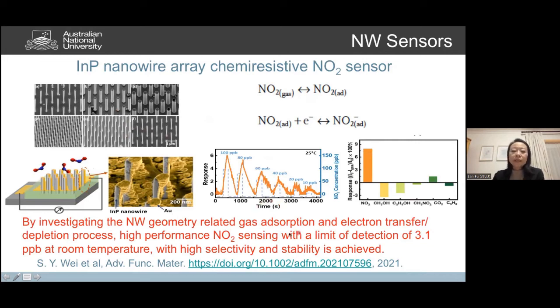We're able to achieve a limit of detection down to the 3 ppb level at room temperature. And it has very high selectivity, as you can see, towards a range of gases, and very good stability. We also found that by changing the geometry of the nanowire arrays, we can tune the response range of the sensor, which is very useful as well. So that really shows that III-V semiconductors can be very useful for nanowire sensing applications.